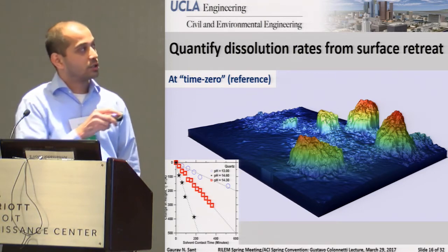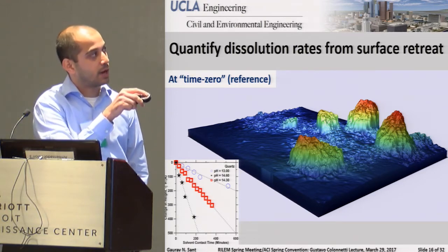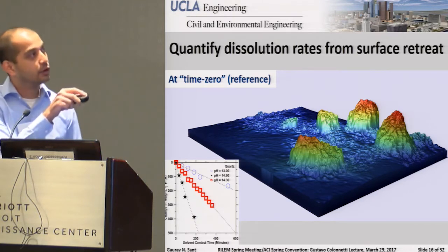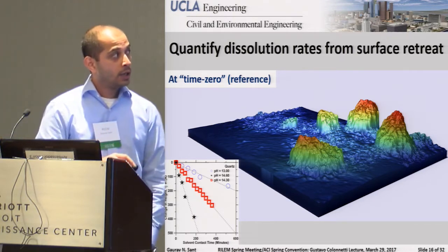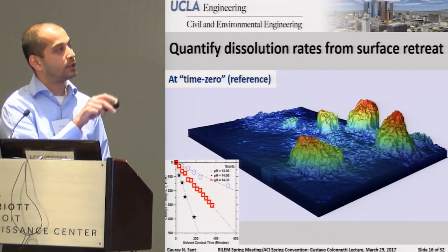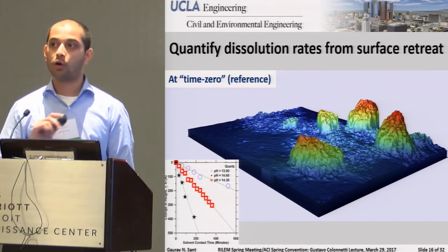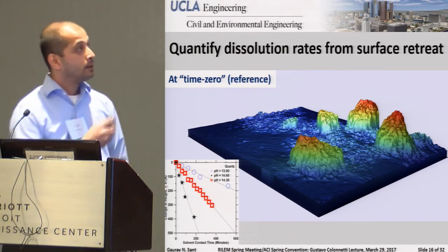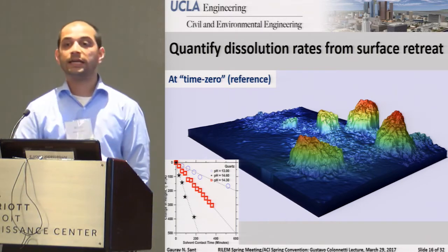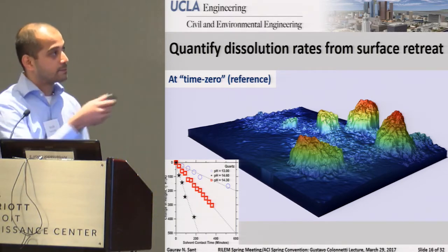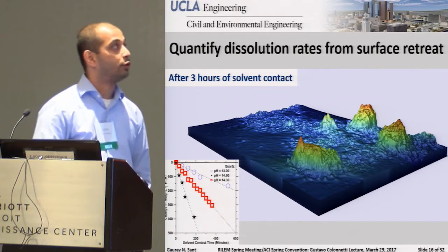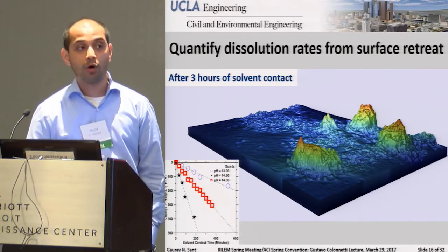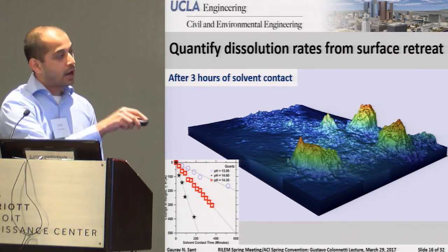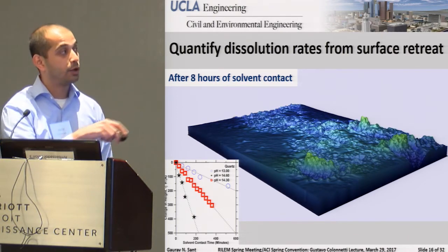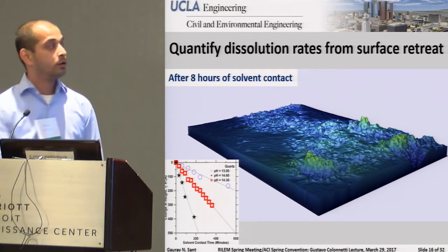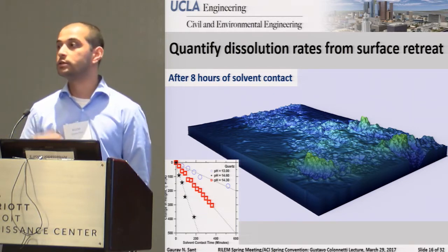But you can imagine that we've got a surface, and this is an inert surface, so this is actually masked with a silicone mask, which is the inert part, so to speak, and you've got some particles on it. As you go out in time, let's assume that I take the surface and I dip it in a bucket of water and I bring it back after a couple of hours. After 3 hours of contact, you can see that the particles are eaten away a little bit. I take this back, I put it back in my bucket, and I bring it back after a few more hours, and you can see the particles are eaten away yet more. If I plot the change in height of the particles as a function of time, and you can do this particle by particle, of course, you can imagine the slope of the line reveals the dissolution rate.